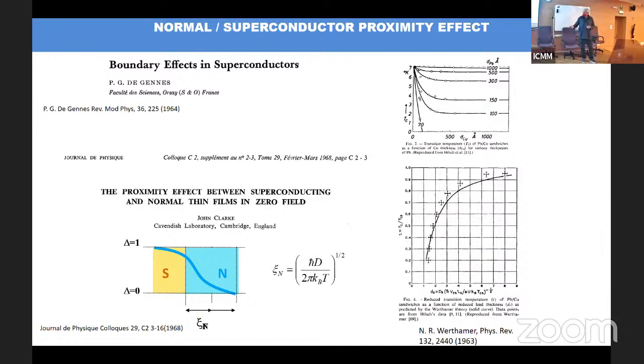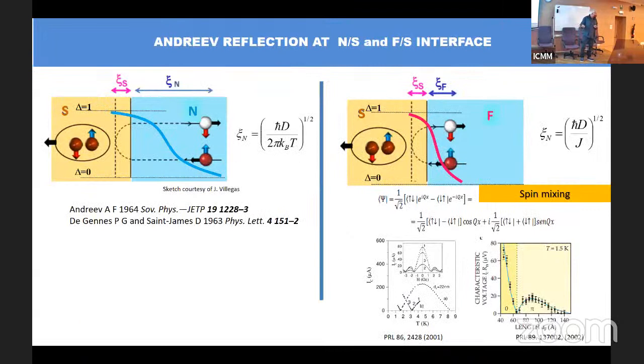In the proximity effect, when a superconductor is placed in contact with a normal metal, the pairing amplitude penetrates into the normal metal over distances which may be quite long at low temperatures. The microscopic mechanism is the Andreev reflection, by which an electron, say spin up, is retroreflected as a hole with opposite spin, right? These are the Andreev pairs. They are phase coherent, right? And there is a pairing amplitude, due to this phase coherence of the Andreev pairs, induced in the normal metal, right? Now, if the normal metal is a ferromagnet, the length scale for this pairing amplitude is considerably reduced due to the effect of the exchange field, right?